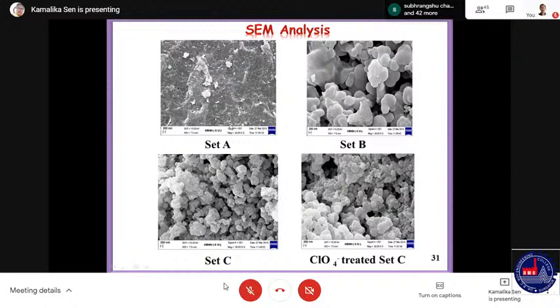The SEM analysis shows that the surface of the non-irradiated sample, that is set A, is flat. However, in set B, we can see very small sized particles. It is 50 minutes irradiation, and lesser size in 24 hours irradiation. With the perchlorate treated set C, there is no change in the morphology. That means perchlorate quietly sits without changing the morphology, and we can see the effect of irradiation very nicely, that the particle size has become very small.